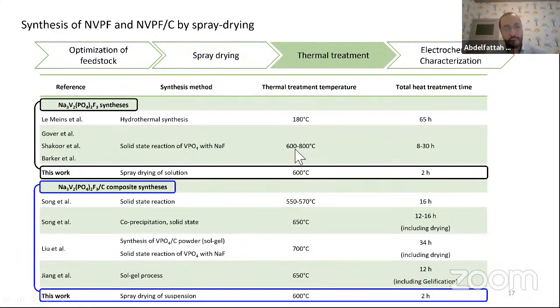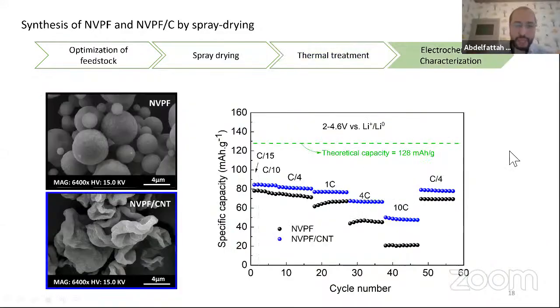Compared to the methods used in the literature, we can see that the spray drying method offers a lower temperature with a very short heat treatment time, which is one of the most critical parameters, because, for example, using solid state, we need between 8 and 30 hours, which is energy and time consuming and not suitable for industrial application. Then we made the electrochemical tests of these two materials, first versus lithium, and we can see that the material with carbon nanotubes shows higher capacity at different C rates, from C/15 up to 10C, compared to the material without any carbon addition, which means that carbon nanotubes increase the electronic conductivity and thus increase the electrochemical performance.